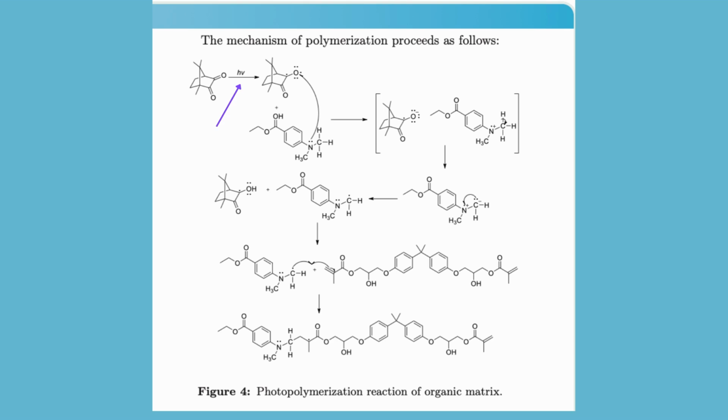Here, the blue light photon is absorbed by the camphorquinone, but given that the half-life of the free radical is short, the co-initiator is used. Then, the co-initiator generates a free radical and then this radical attacks the terminal carbon-carbon double bond to develop a homolytic rupture. Then, this radical attacks other double bonds and initiates a chain reaction that produces a cross-linking polymer.